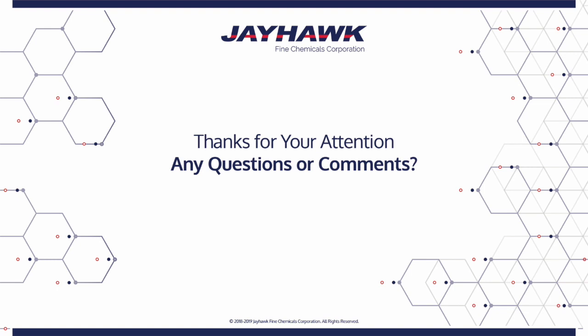Thanks for your question. Boris, I may just follow on with a couple of comments on that. The consideration is the understanding needs to be that BTDA is a tetrafunctional curative, and so if, as Boris indicates, you're on stoichiometry, your cross-linking gets so extensive that in the end you actually will end up with a material that can be quite brittle, and so that's really what's driving the need to be off stoichiometry.